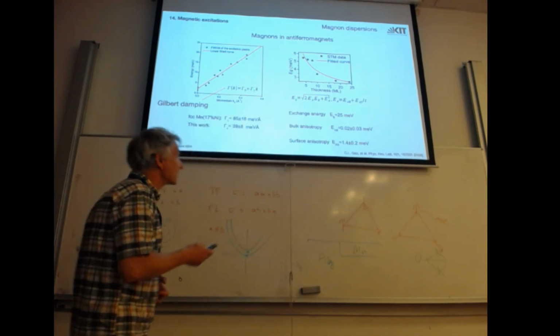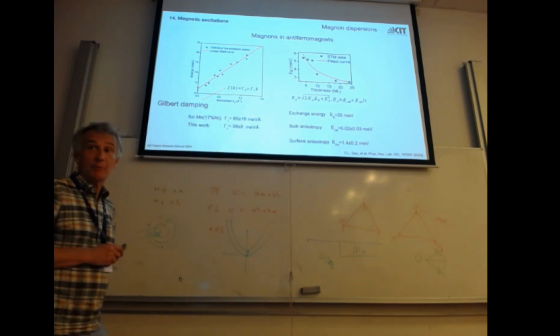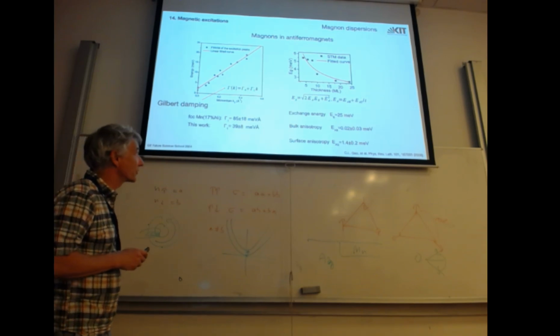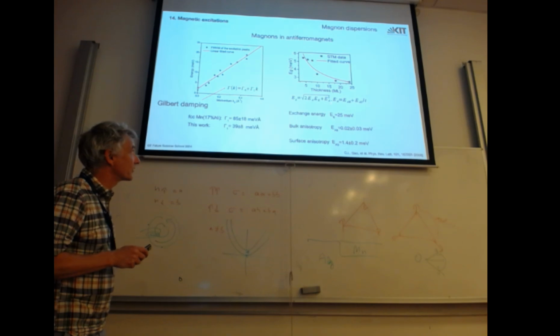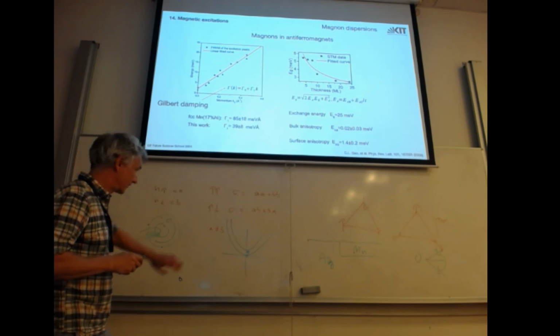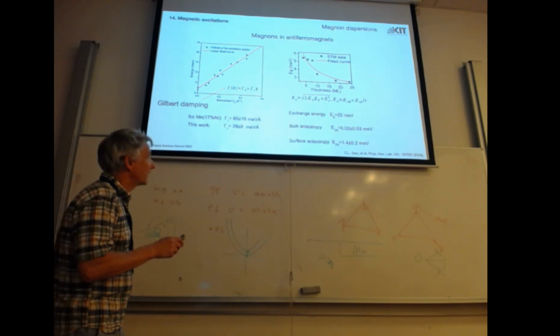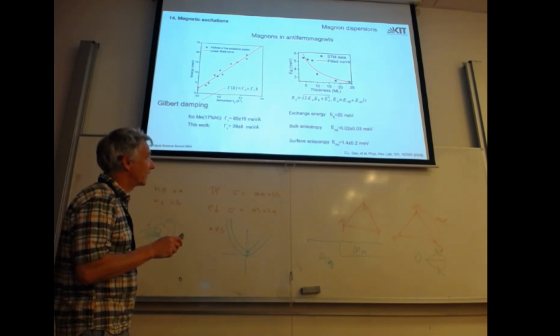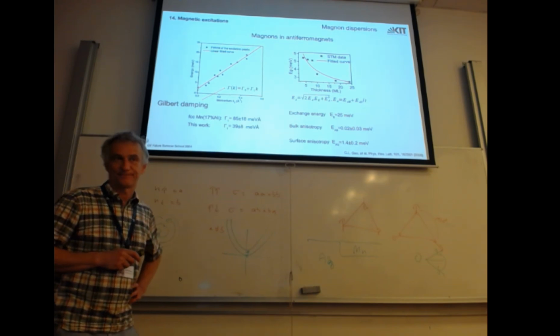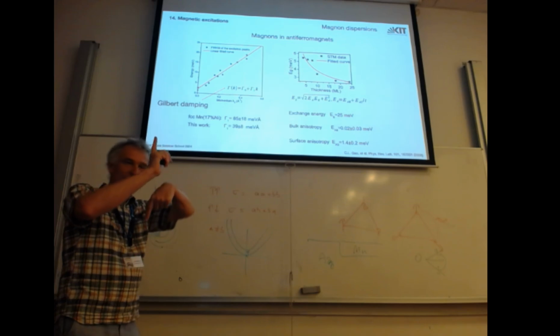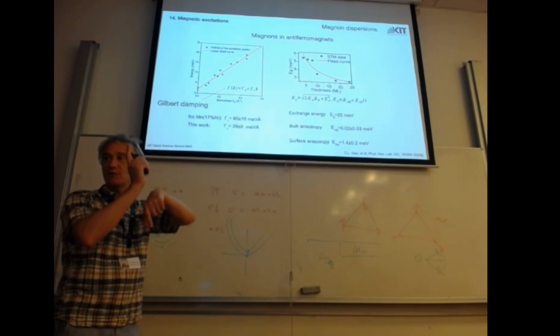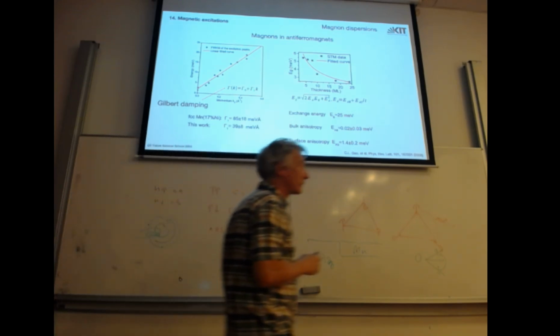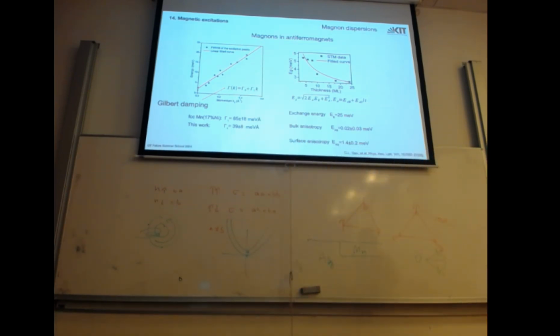For antiferromagnets, this is a bit different. There's also a gap due to this anisotropy. So E anisotropy is the anisotropy energy, and it goes like the square root of this E squared. It's exactly like here. But there comes a second term. This is the anisotropy times the exchange. This comes from the fact that in an antiferromagnet, two spins are precessing, and there will be a coupling between those two spins when they are precessing.